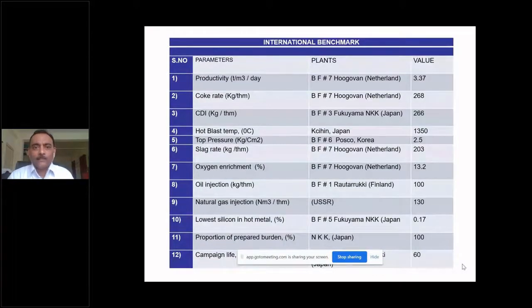There is one furnace in Japan in which the coal dust injection reaches up to a level of 266 kg per ton of hot metal. Hot blast temperature in one of the furnaces in Japan, 1350 degrees centigrade. Top pressure 2.5 kg per centimeter square, very high. The furnace needs very good strength. Slag rate 203, very small. Oxygen enrichment up to 13.2. Oil injection 100. Natural gas 130 normal meter cube per ton of hot metal. Silicon very less, 0.17.